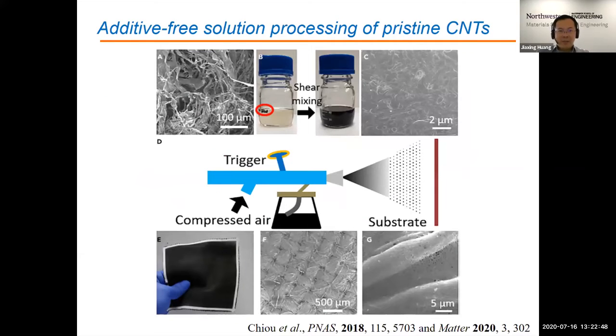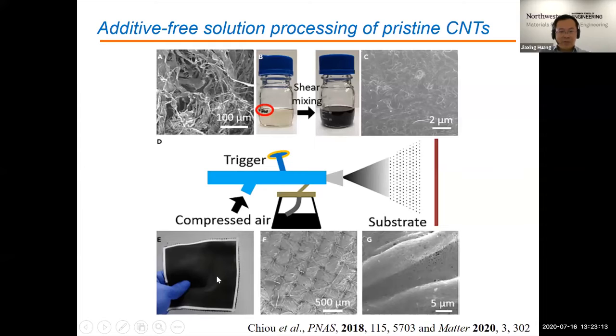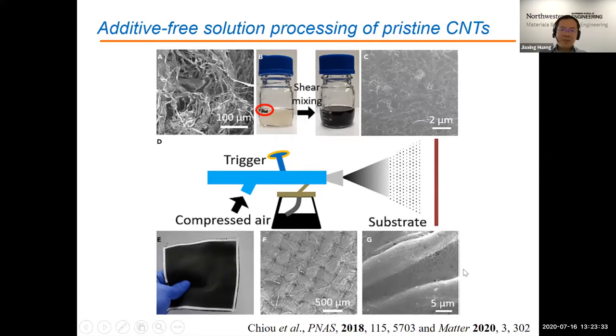In terms of carbon nanotubes, we have been developing additive-free solution processing techniques that can disperse pristine carbon nanotubes in high throughput. One of the most recent examples is that we can disperse single nanotube powders in a solvent cocktail. You can adjust the composition of the solvent cocktail to make it suitable for airbrushing to coat various textile surfaces. There has been a lot of effort now using these kinds of surfaces as sanitizing textiles in COVID-19 — the idea being that you can photo-thermally or electrically heat up this layer to inactivate pathogens.